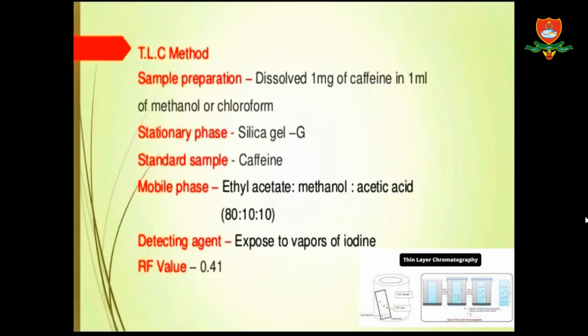Next slide, ma'am. For sample preparation, we dissolved 1 milligram of caffeine in 1 ml of methanol or chloroform. We took the stationary phase as silica gel and the mobile phase as ethyl acetate, methanol and acetic acid in the ratio of 80:10:10. So we detect the agent by exposing it to vapors of iodine. So the Rf value which we got is 0.41.